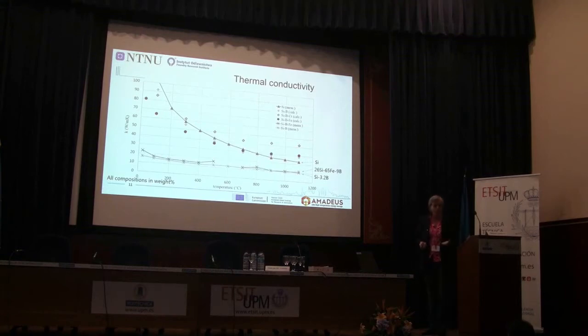Again, this is work in progress, because this is a very fragile material as it crushes down very easily. So when we start to make samples of it and cut it, we can introduce micro cracks, which will affect the thermal conductivity. So we need to find a way to measure these alloys a bit better.